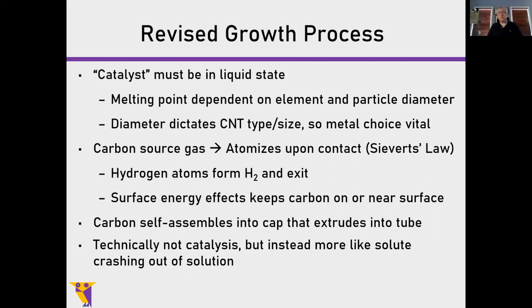But the carbon source does not undergo any type of catalyst process. In fact, it just breaks apart. It dissolves, for want of a better term. And surface energy means that the carbon is going to stay near the surface. It's going to lower surface tension by remaining not inside of the particle. It's going to remain on the surface, which is great because it's going to move around a lot. So the carbon will self-assemble into a cap that extrudes into a tube.